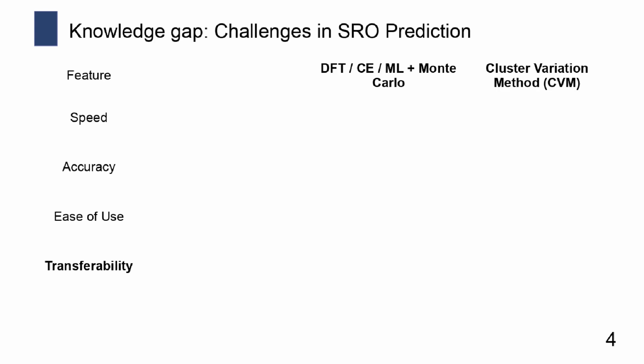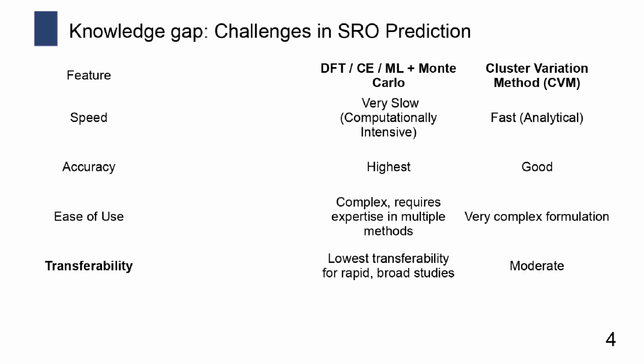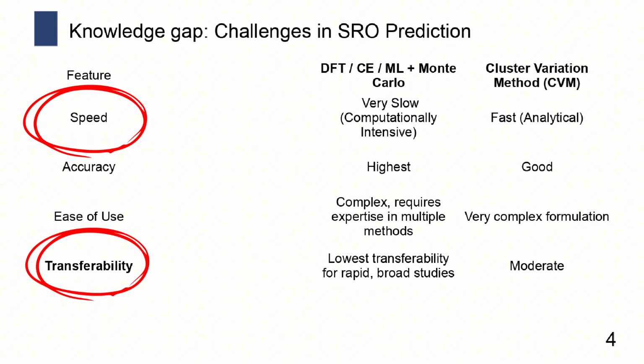Our current methods to predict short-range order are density functional theory, cluster expansion, and other sub-methods. They work well. However, they are computationally expensive and are not transferable. That means that for each new calculation with a new composition, they require starting from scratch, from the beginning, meaning that fast screening of a vast compositional space is impossible for these methods.